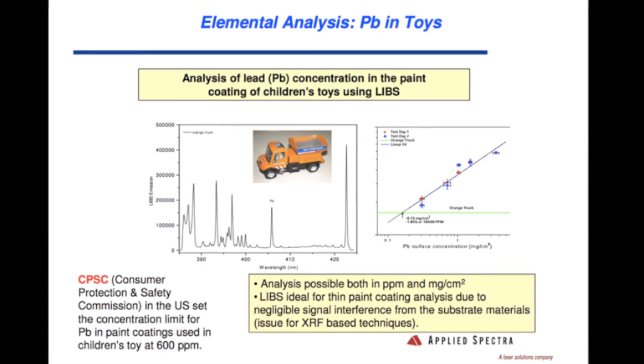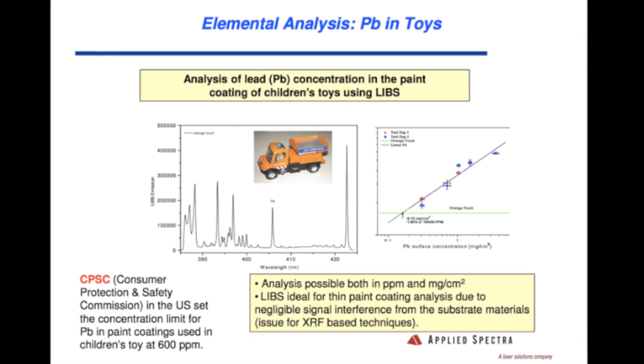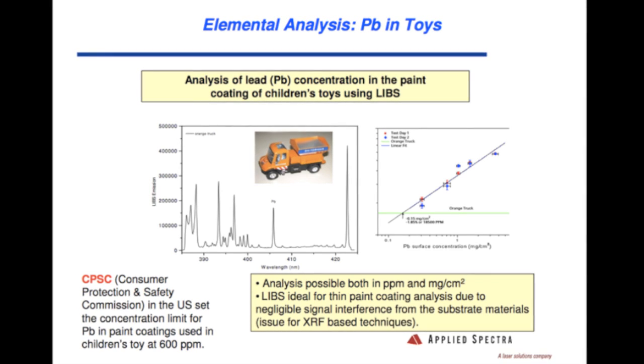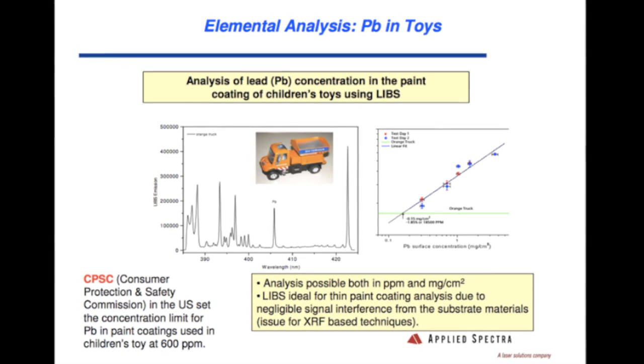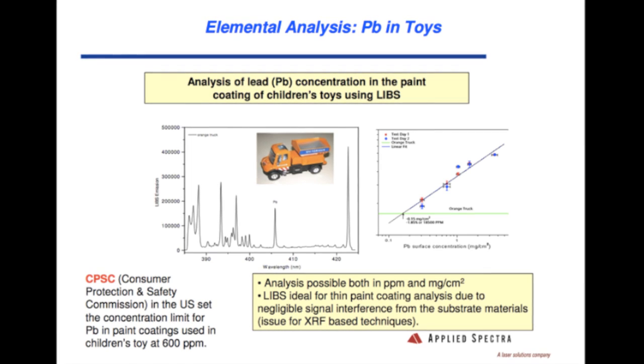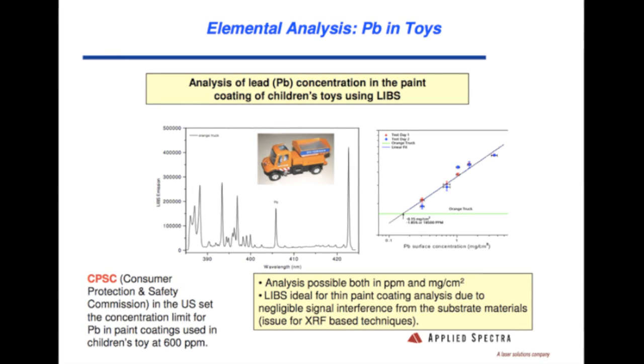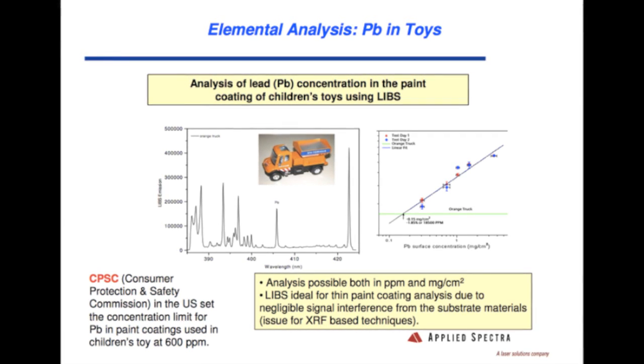So we tune our spectrometer. We did a calibration plot with some standards for this particular yellow paint. And we basically go in there, you hit that with one laser shot, measure the intensity, fit it on your analytical curve, and you say how much lead was in that toy. That's as simple as it is, okay? So that's elemental quantitative analysis.